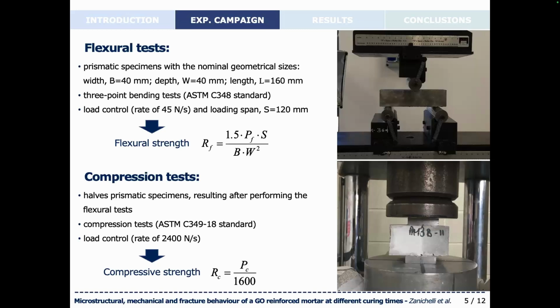So, as far as the mechanical tests are concerned, flexural tests, compression tests, and fracture toughness tests have been carried out for both plain mortar specimens and GO-reinforced specimens at different curing times. In particular, for each curing time considered, 3 prismatic specimens with the nominal geometrical sizes shown here have been subjected to 3-point bending tests in order to determine the flexural strength.